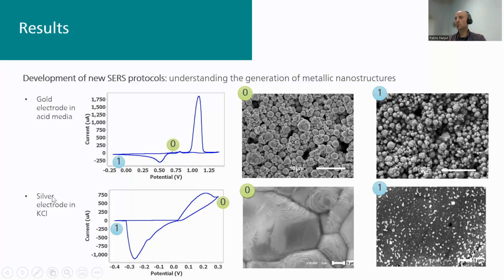And the same, we can get it with a silver electrode. So in the case of a silver electrode, imagine that just a very low potential at plus 0.3 volts, we can oxidize some of the silver surface. So this is the standard initial silver surface. When we oxidize the silver surface in presence of potassium chloride, we can generate some silver chloride deposited on the surface of the electrode. And when we reduce this silver chloride, so the silver plus is going to metallic silver, we can get these silver particles in the order of tens or hundreds of nanometers in the surface of our electrode.